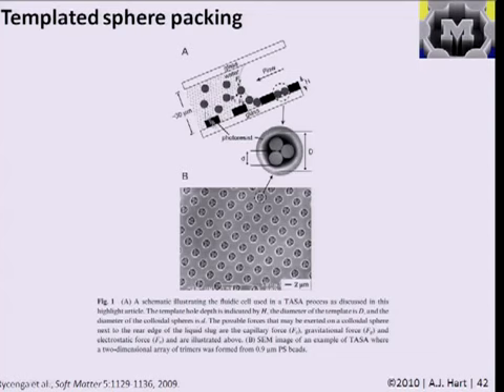And on one of the glass slides, they had patterned a photoresist, and the height of this pattern was maybe a couple of microns, and the width of the holes was also about a couple of microns. And when they took a solution of polystyrene spheres in water and passed it through the gap between these glass slides, the interactions between the spheres and the glass were such that they stuck in these cavities. And indeed, what they studied was how the size of the cavities related to the ability of particles of a certain size to pack. So in this case, when they had particles of 1 diameter, small d, and a cavity